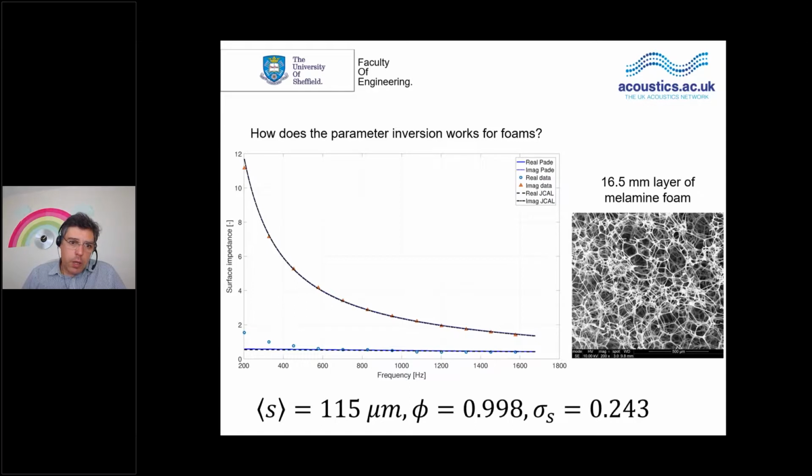Yes, the physics will be different, but we use the Pade approximation, which is nice to use because it brings together low and high frequency regimes. That's why I started my presentation with the viscous and thermal characteristic frequencies, because these frequencies separate the low and high frequency regimes, and in the middle the behavior is a bit complex.